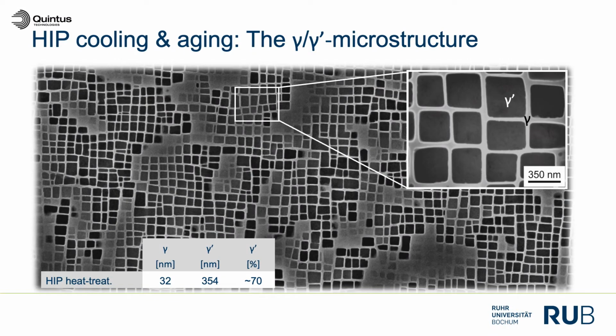And this is a very positive influence on the microstructure that evolves during this cooling from the high temperature HIP regime, because we establish a very fine and uniform gamma-gamma prime microstructure after quenching. And this has a very positive effect because we precipitate very fine gamma prime cubes, and when we age them, they grow to a final size of, I don't know, 350 nanometers we found out.